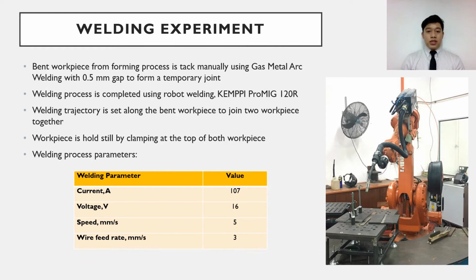So the welding trajectory is set along the bend workpiece to join the two workpieces together, and the workpiece is held still by applying a clamp on both ends. The welding process parameters are shown in the table, where the current used is 107 ampere, 16 volt, 5mm per second speed, and the wire feed rate is set at 3mm per second.